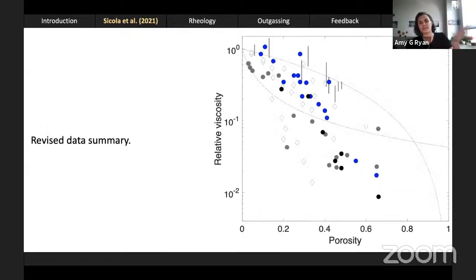So if I put Stefania's data back into this data summary, the blue circles here are her gas-filled bubbly melts, and these black ones here are the drained melts populated with drained pores. And all of the gray symbols here are the samples I showed earlier that have the same geometry as Stefania's work. We can't necessarily say whether they were filled with bubbles or pores at the time of deformation, because often the experimental methodologies included some quenching stage. So still lots to do.